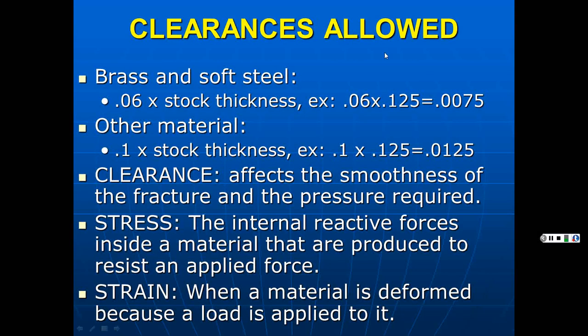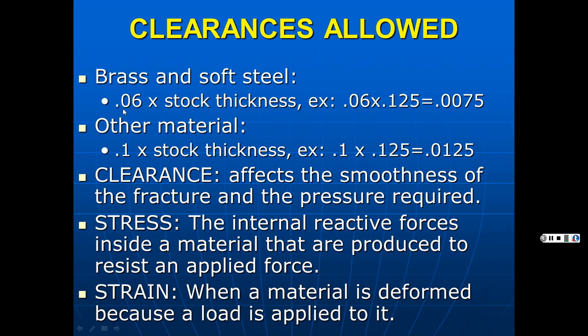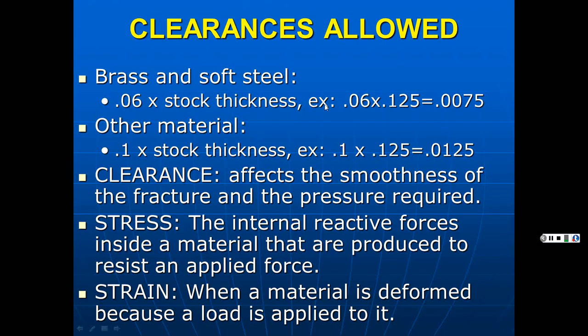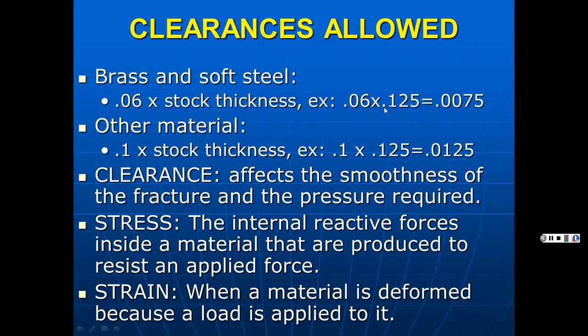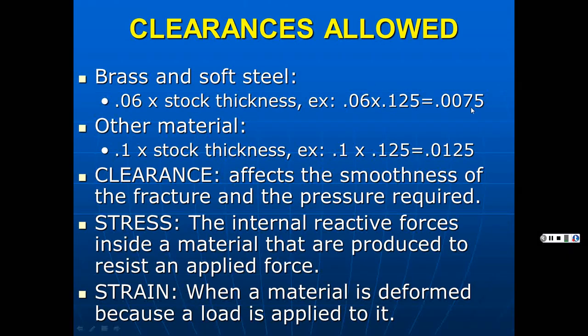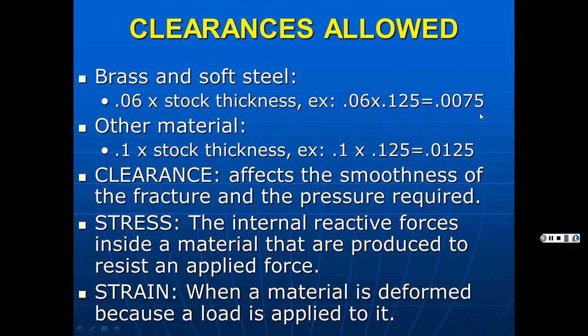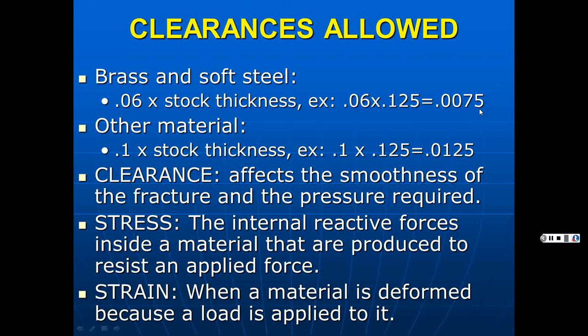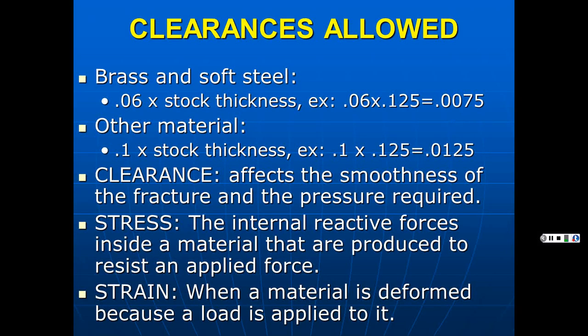And then some of the clearances allowed. If you look in brass and soft steel, the multiplier there is 0.06 times whatever the stock thickness. Here we have 1/8 of an inch, 0.125 times 0.06. So here's our gap. 7.5 thousandths is how much gap we should have. That gives you a ballpark. You try that. If that doesn't look good, you go with maybe a little more gap or a little less gap and see what happens. Run a few samples before you run thousands of these and ruin them all.